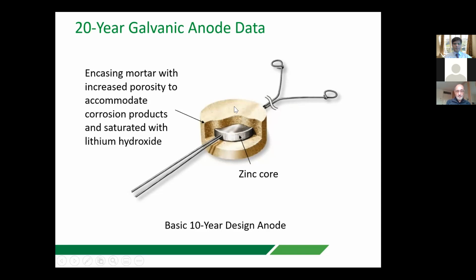So we had to encase it in a cementitious material that will maintain the activity of the zinc. And the way we achieve that is to include a saturated amount of lithium hydroxide, i.e. lithium hydroxide powder mixed into the cementitious material that will maintain the pH well above 14, and it will keep it at a constant pH because it's a saturated solution. It means that it acts like a buffer, and therefore that will continually maintain the activity of the zinc product.